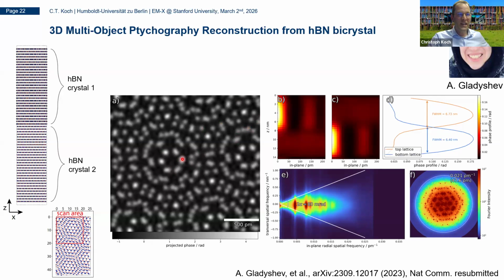And if we now plot a line scan through these atoms here, you can see there is an atom at the bottom and at the top. And this is the atom at the top, which then stops in the top layer and then it disappears in the bottom layer. Sorry, these are 2 different line scans. I apologize. 2 different line scans because they always start at the center of an atom. But this is an atom in the bottom slice where you can see really it only appears in the bottom slice and not on the top. And from that, we can roughly determine the Z resolution to be approximately 1 nanometer.